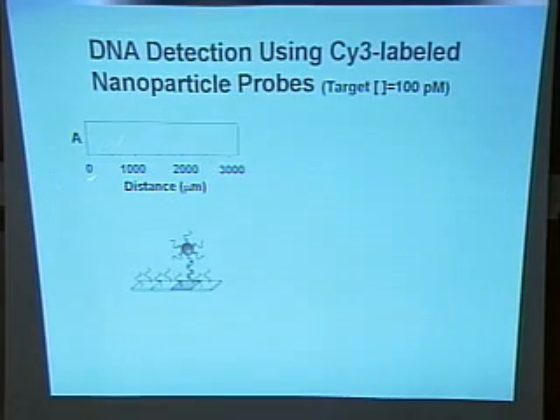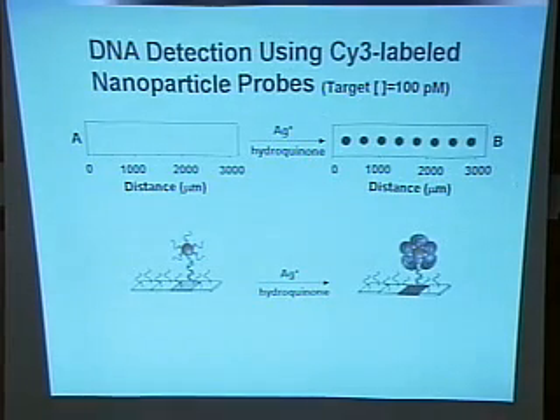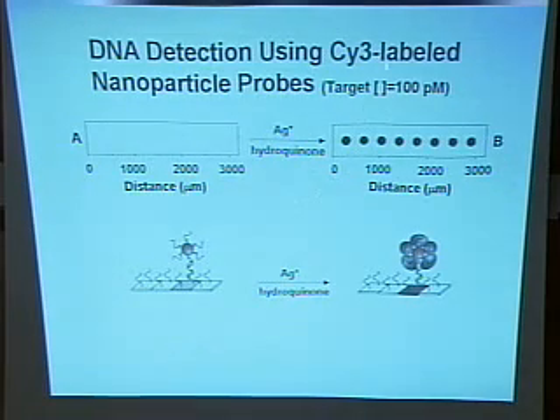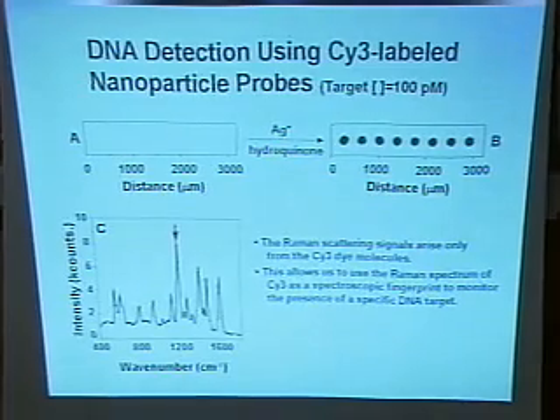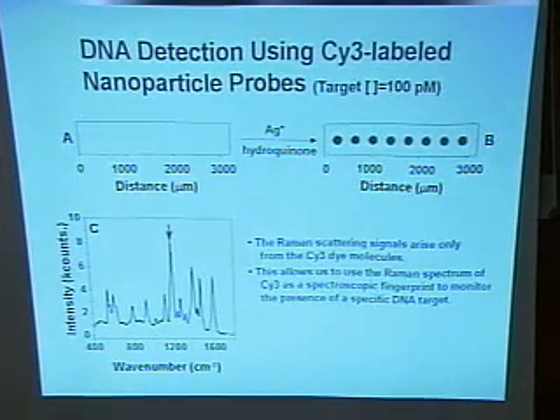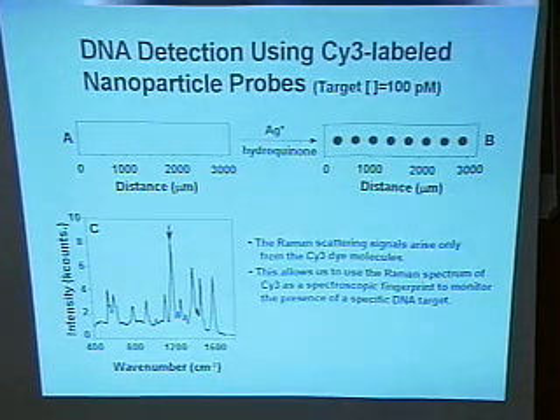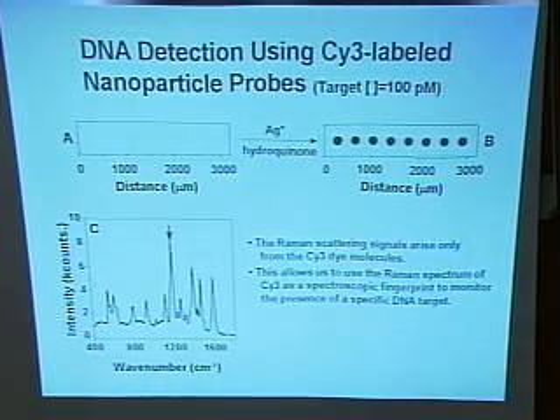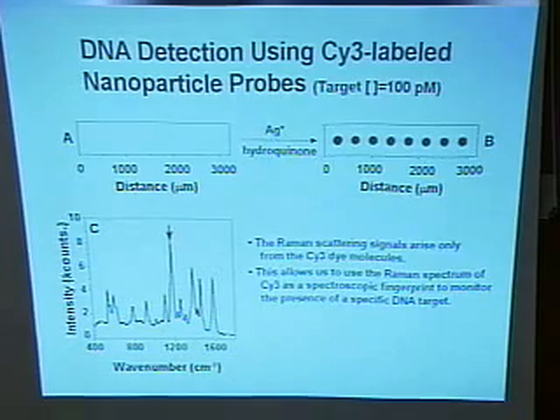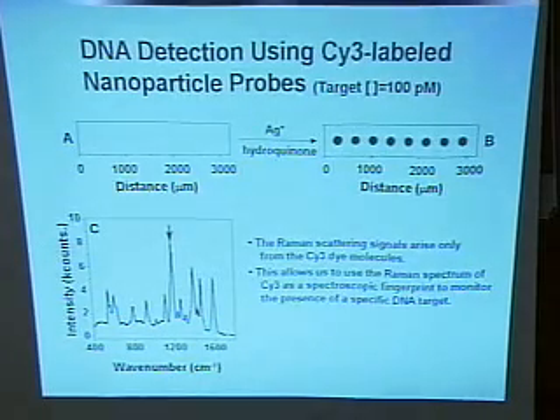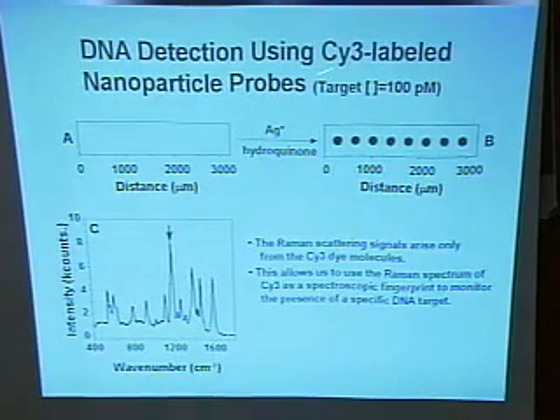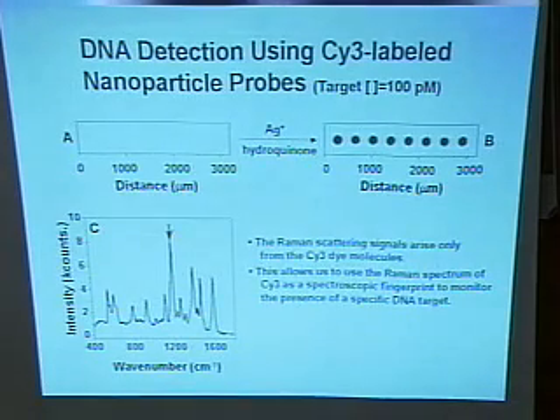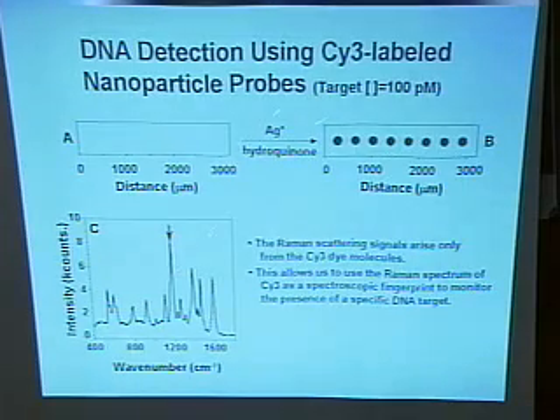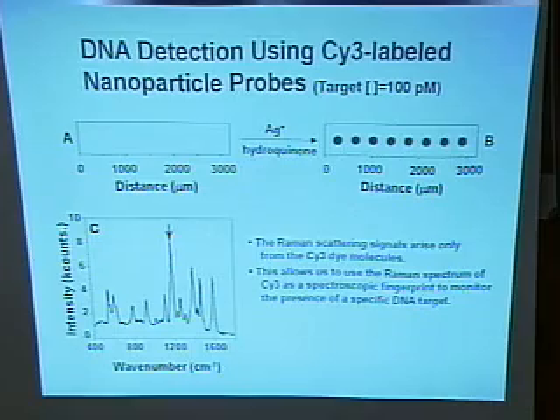Here is a typical chip after target and probe hybridization. You couldn't see anything. However, after the silver staining process, the black spots come out. Then you measure the Raman spectrum from each spot. You will find very huge scattering signals come up, which come only from the label, the Cy3 molecules. It's not from oligonucleotides and other chemicals used for this detection. So that gives us an advantage. We can use the Raman spectrum of this Cy3 dye as a fingerprint to monitor the presence of a specific target.